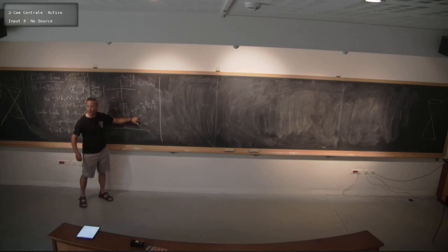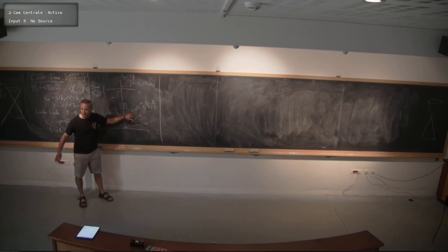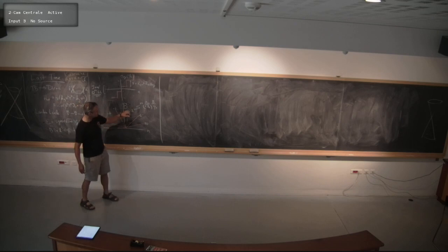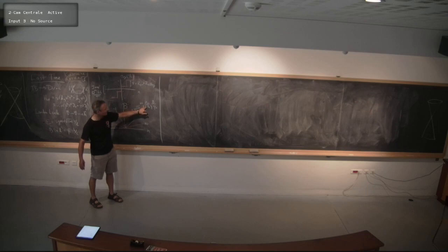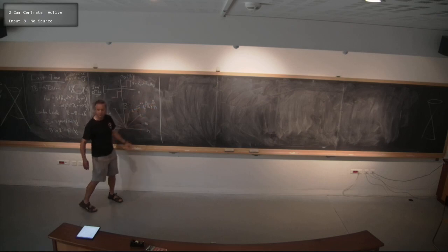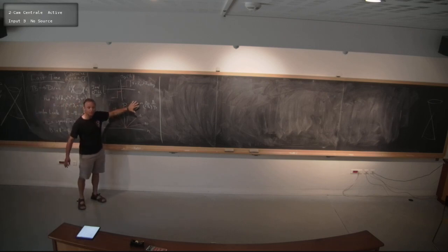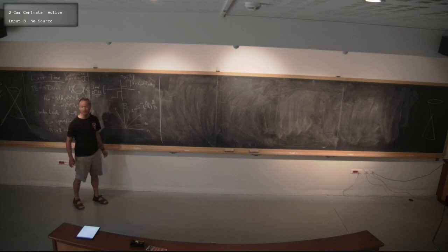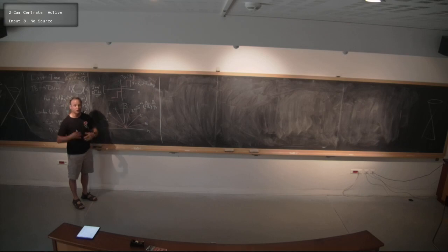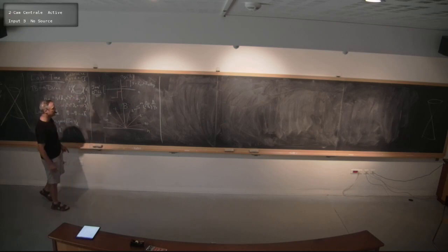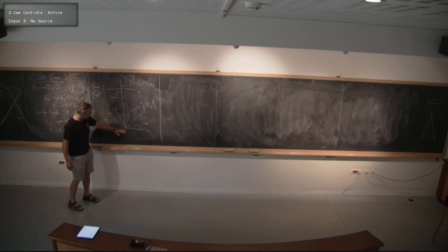These integers correspond to the Hall conductivities. They're actually the inverse of the slope on this plot. You can easily see this is just the condition that N is the number of filled Landau levels, so sigma xy divided by the integer quantum Hall quantum times the number of states per Landau level, B over phi naught. This is actually related to a famous formula called Streda's formula, which relates the density to magnetic field via the Hall conductivity. It's a very general result that holds when adiabaticity is valid, which means generally when the system is in a gap. So these kinds of plots are used heavily in twisted bilayer graphene to try to analyze